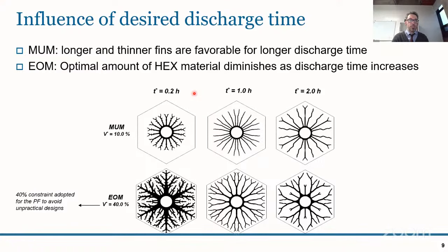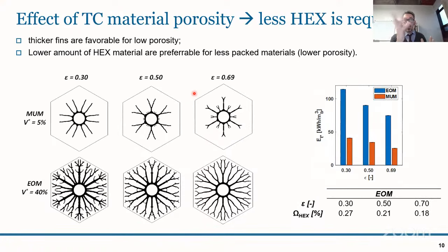I'll spend the last minute to comment on the porosity aspects. One of the key challenges is that typically, after a few cycles of these reactors, there is agglomeration of the material, which translates essentially into an effective porosity that diminishes over time. So we looked at how heat exchanger design can mitigate this reduction of porosity and therefore the more difficult transport of the sorbate through the reactor. So we try to optimize, obviously, for an entire history potentially of utilization of the thermochemical storage reactor.